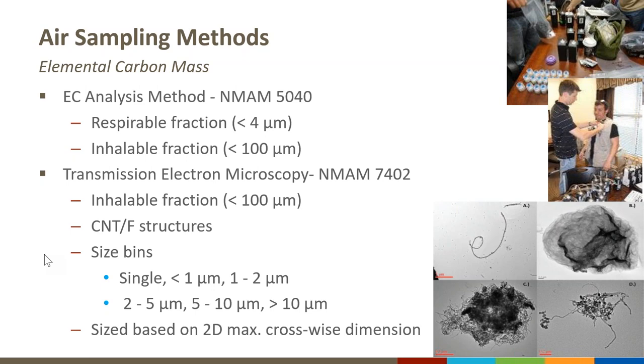So a structure could consist of a single fiber, as you see in that image below, or typically what we would find are these structures would be more agglomerated materials, and they could consist of a few individual fibers, or they could consist of maybe thousands of individual fibers. To try to differentiate between single fibers or small agglomerates compared to larger agglomerates, we decided to develop six different size bins that we place these agglomerated materials or single fibers into based upon their two-dimensional and crosswise dimension. So these bins consisted of a single fiber bin, a bin for agglomerates less than 1 micron, agglomerates between 1 and 2 microns, 2 and 5 microns, 5 and 10, and then greater than 10 microns. Next slide, please.